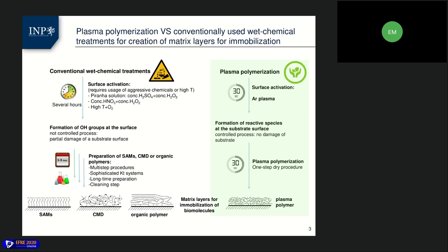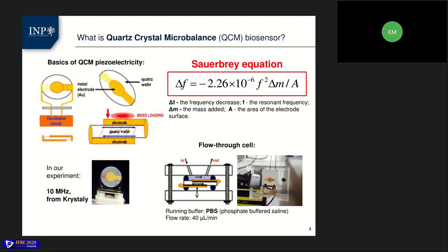As an alternative, deposition of thin functional coatings by plasma polymerization can be employed, which is a one-step, solvent-free, eco-friendly process. The plasma polymerization has already been applied for deposition of thin films containing carboxyl, amine, or anhydride groups. The transducers used for biomolecular detection in this study were the quartz crystal microbalance and surface plasmon resonance sensors. QCM is a relatively simple and sensitive device consisting of an AT-cut quartz disc plate covered with evaporated electrodes on both faces, allowing further immobilization of sensitive biorecognition elements. Alternating voltage applied to this electrode induces shear deformation of the crystal.